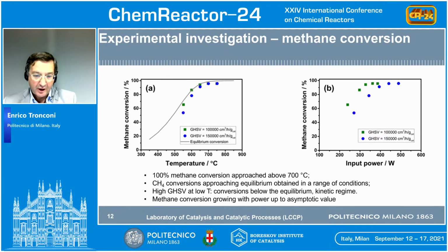Methane conversions are plotted against the outlet temperature measured at the exit of the catalytic foam. And you can see here that as a result of strongly reduced heat and mass transfer resistances, we were able to achieve methane conversions approaching the equilibrium curve across a full range of conditions. And actually, we reached essentially a complete methane conversion at temperatures above 700 degrees C.